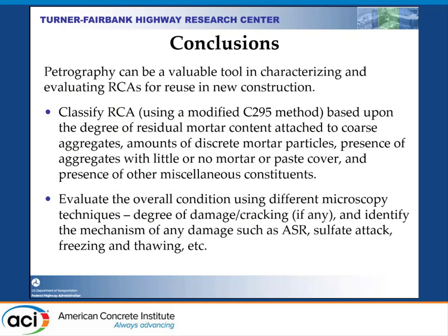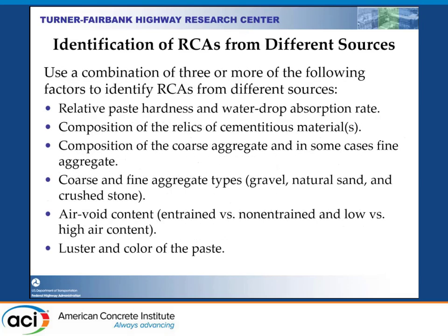In conclusion, petrography can be a valuable tool in characterizing and evaluating RCA for use in new construction. Classify RCA using a modified C295 method based on degree of residual mortar content, amount of discrete mortar particles, presence of aggregates with little or no mortar cover, and presence of other miscellaneous constituents. Evaluate overall condition using different microscopy techniques, degree of damage, cracking, and identify mechanisms of damage such as ASR or sulfate attack. To identify RCA from different sources, use a combination of three or more factors: relative paste hardness and water drop absorption rate, composition of cementitious material relics, composition of coarse and fine aggregates, whether aggregate is gravel, natural sand, or crushed, air void content, and luster and color of the paste. Thank you.